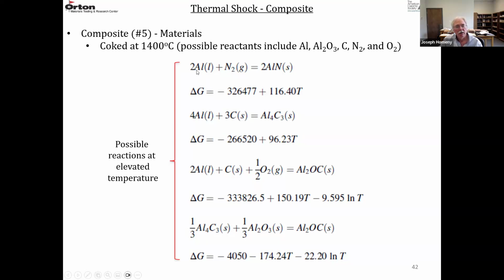Al plus nitrogen forming aluminum nitride, Al plus carbon forming an aluminum carbide, Al4C3, aluminum plus carbon plus oxygen forming an aluminum oxycarbide, Al2OC, and then Al4C3 from this reaction plus Al2O3, again forming this aluminum oxycarbide, Al2OC. They put down the Gibbs free energy change for all of these reactions.